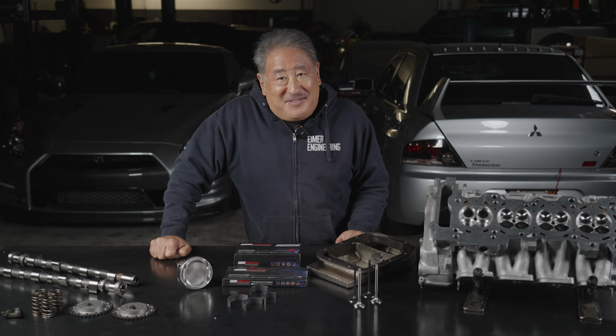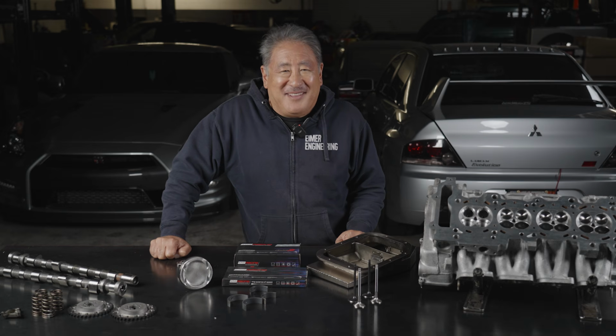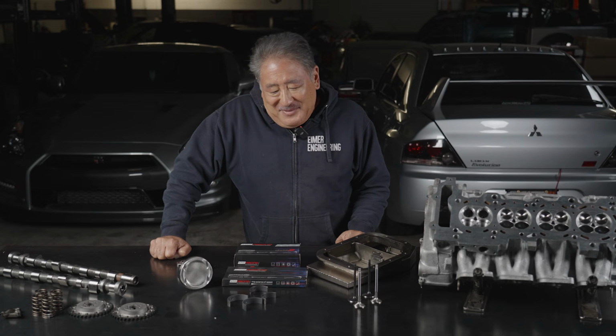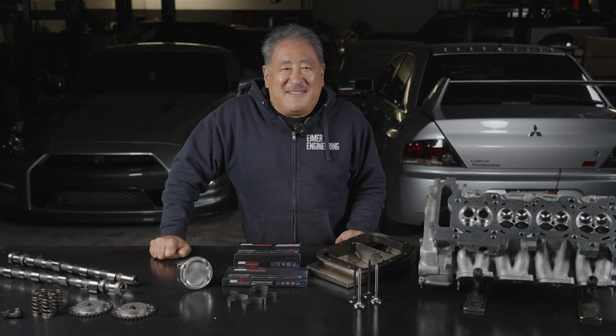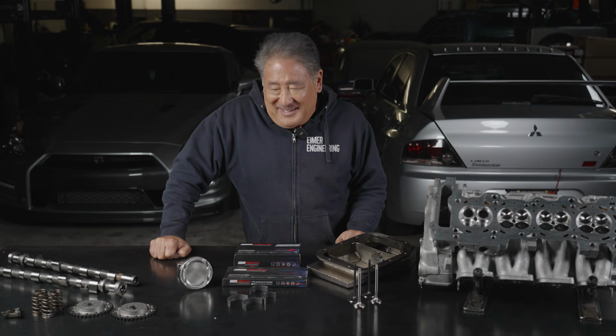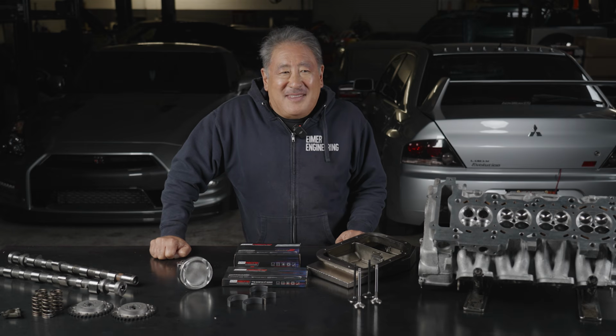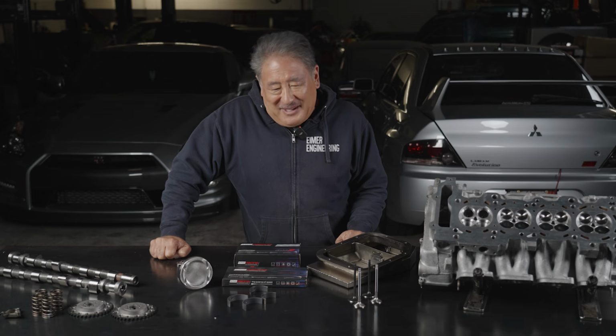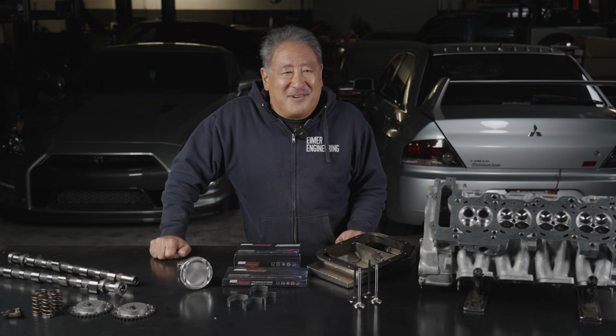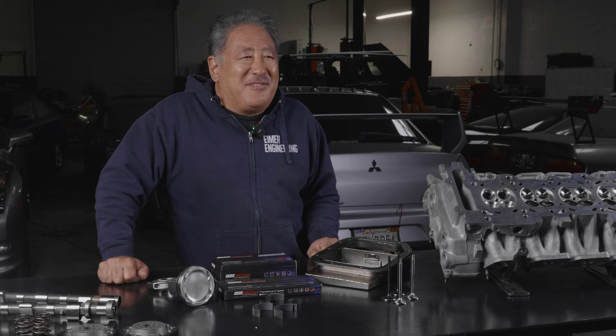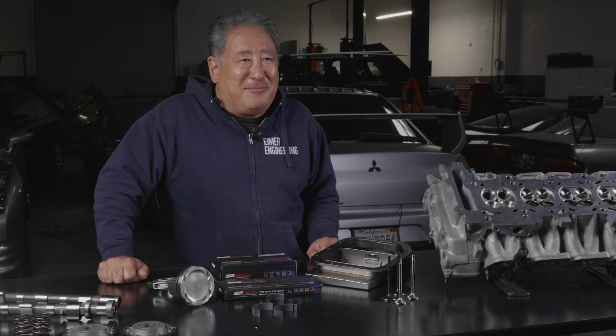Now it's a racing bearing, so it's not gushy and it can't embed a lot of dirt like a stock bearing, but that's the drawback. What really sets the XPC apart is it has a coating. Now it's not just a regular coating like a typical bearing, but it's a polymer and it's filled with copper nanoparticles. So the copper nanoparticles are actually pretty hard. They give the coating some body, and it actually increases the load bearing capacity of the bearing by about 15%.